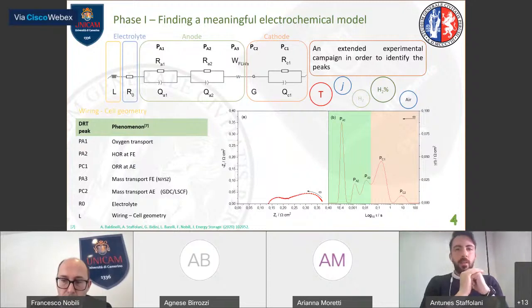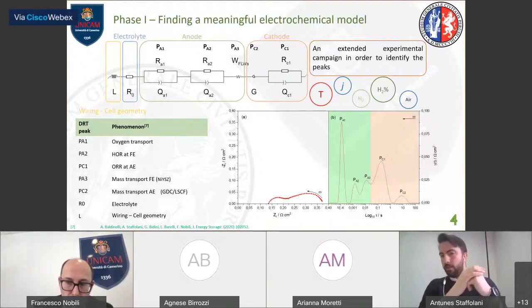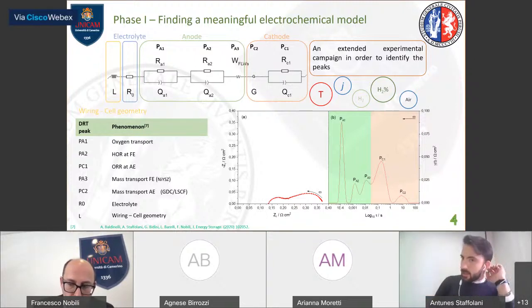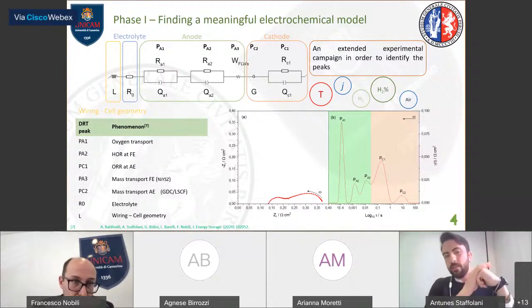And regarding phase one, we applied an extended experimental campaign varying several operating parameters, such as the temperature, the current density, hydrogen percentage and flow in the anode, and the airflow in the cathode. And we have seen 5 different time constants, 3 of them related to the anode, which were the hydrogen oxidation reaction, the hydrogen gas diffusion, and oxygen transport, and 2 related to the cathode, the oxygen reduction reaction and the oxygen diffusion.